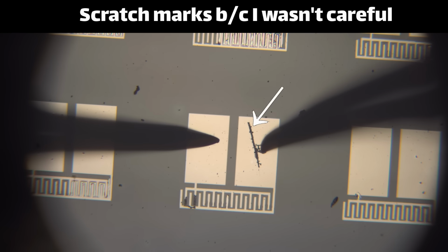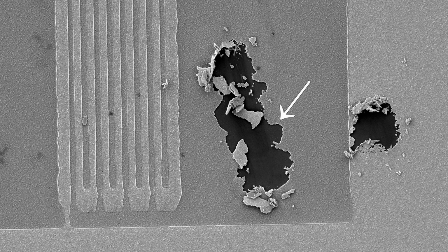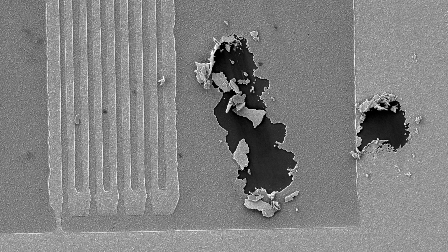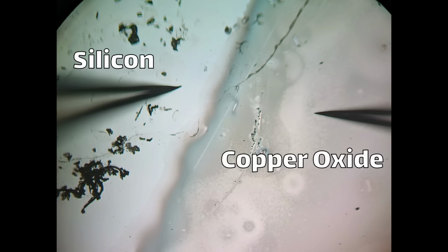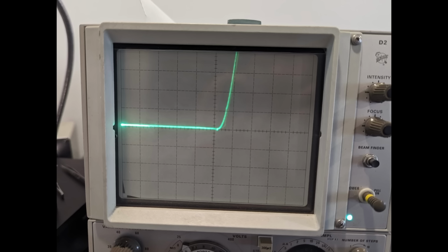The probe tips are very sharp and very hard because it's tungsten. So it's definitely possible that we scratched through that silicon dioxide layer and we're actually probing the underlying silicon. The copper oxide itself is really fragile, and the silicon dioxide layer is pretty thin, so it's not a crazy thing to expect might happen. In another test, I probed the bare silicon and the copper oxide, and the results look suspiciously similar.